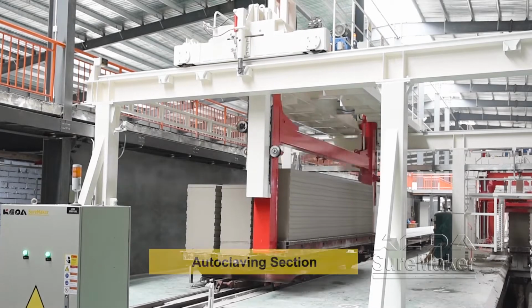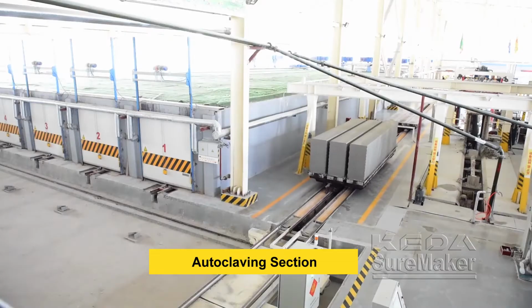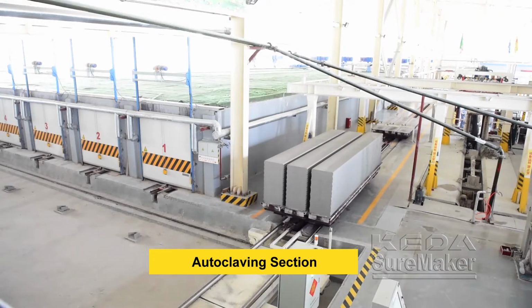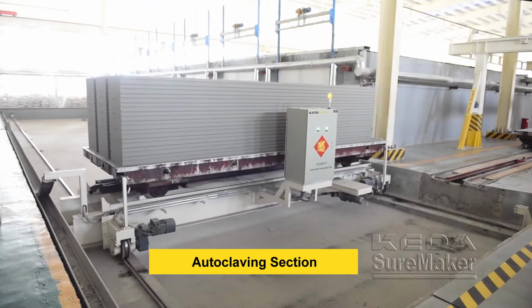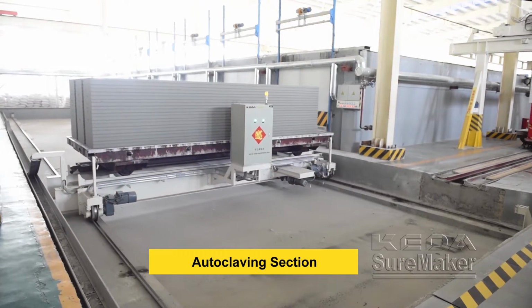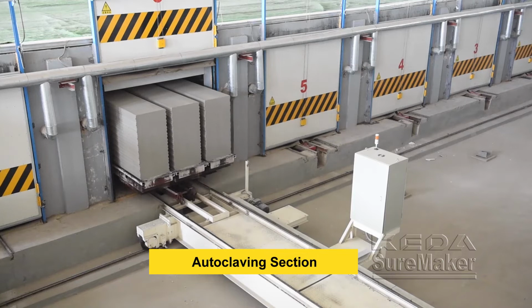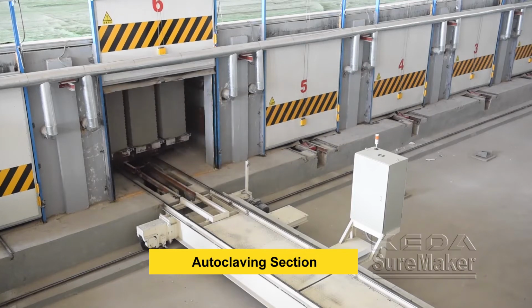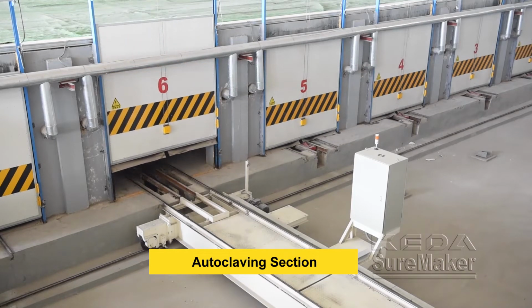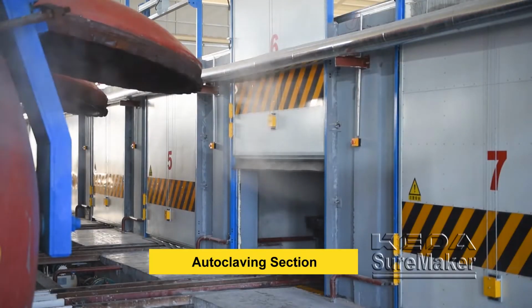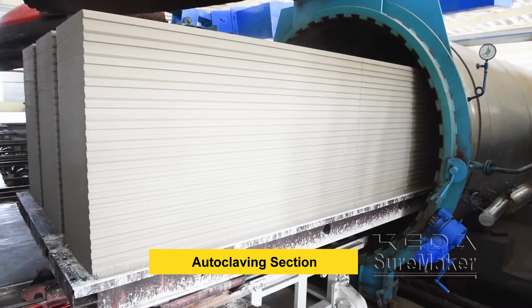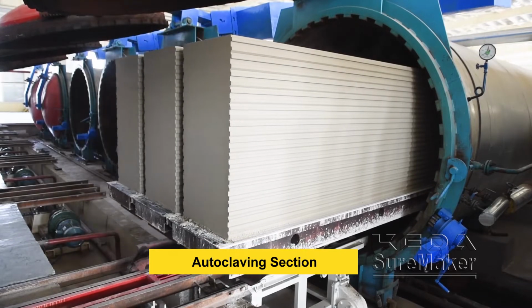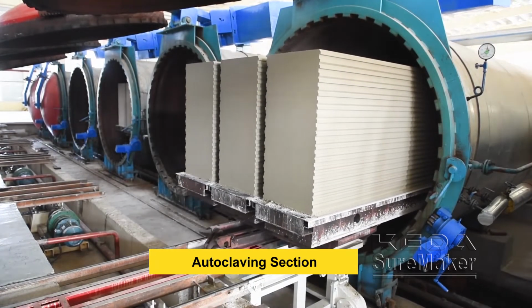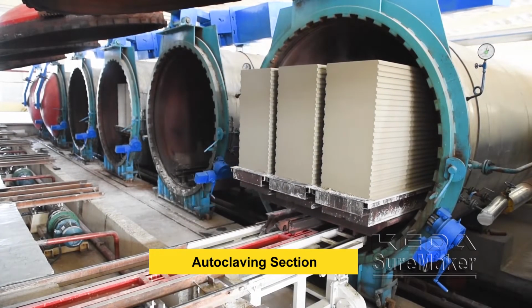The semi-finished product stacking machine transfers the green cakes together with side plates on the 3-mold curing car. Then, the ferry car will take them for grouping before autoclaving. After grouping, 3 molds curing cars will be pushed into the autoclave for curing 10 to 12 hours under 200 degrees Celsius, 1.2 megapascal.